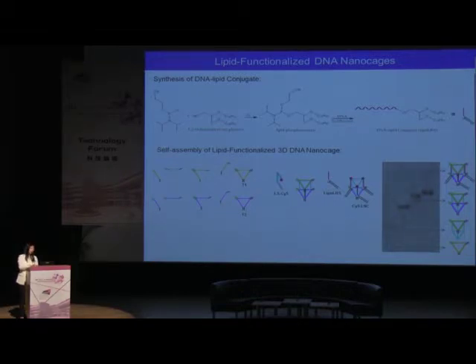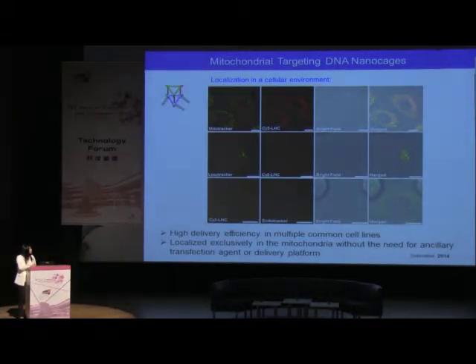And surprisingly, we found that these lipid functionalized DNA cages can be internalized by many different cell lines with high efficiency, and all of them localized exclusively in the mitochondria without any use of transfection reagent or even the delivery platform. So we believe that this modification is good for us to further study the biofunctional properties of the cages in the subcellular environment.